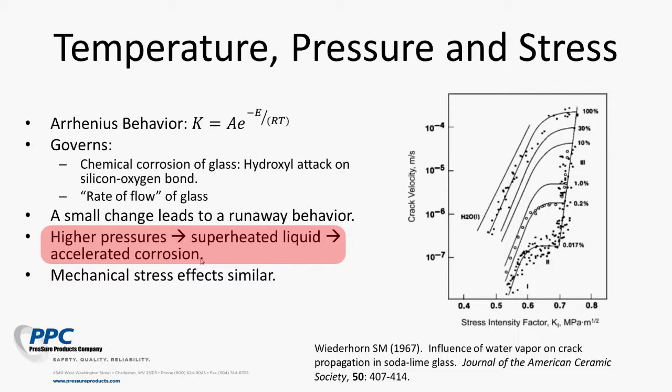As I said in the previous video, you can make the glass hold more pressure by making it thicker. But if the high pressure is actually causing enhanced corrosion, then a large margin of safety in the pressure scale means nothing at all. A thick piece of glass will corrode away just as well as a thin piece of glass and start leaking just as quickly.